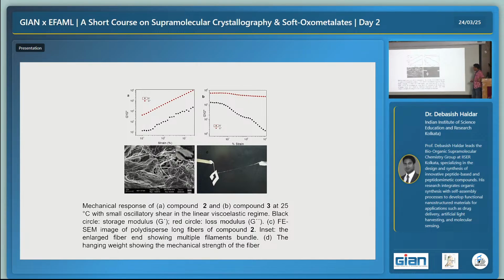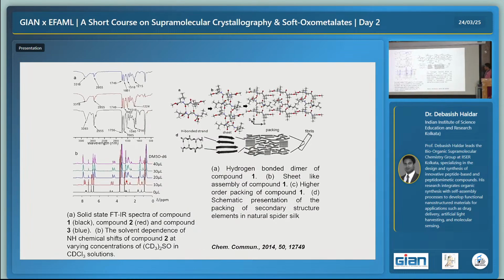It shows that the compound is fiber-like in nature, and if we zoom in, the fibers are actually made of small fibrils. The fibrils are entangled to make the fibers, and the fibers can take some weight. Then we studied the structure of the fiber using FTIR, NMR, and obviously the X-ray structure. What we feel is that the compound forms anti-parallel beta sheet-like structures, which help to make a higher order assembly, a higher order packing, making the fiber. The fiber is strong enough to take a certain amount of weight, and this actually mimics the natural spider silk.